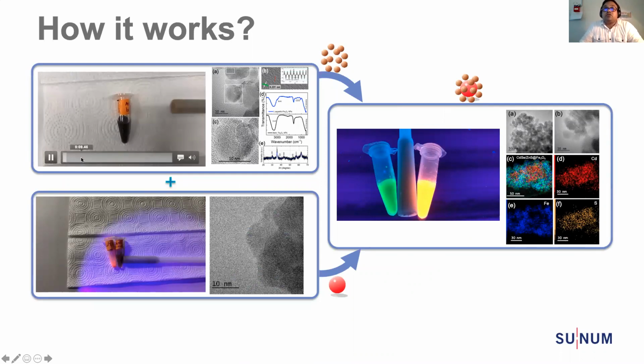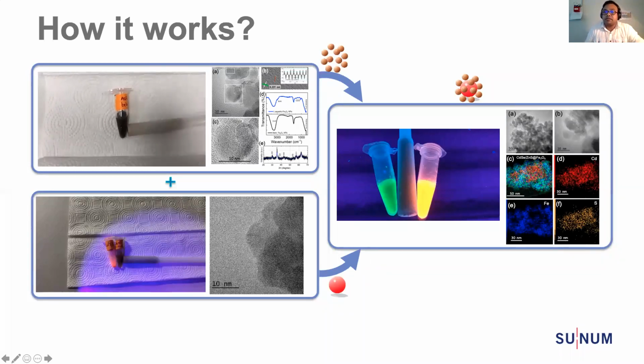First we had to synthesize very precise size-controlled magnetic nanoparticles. We employed density gradient centrifugation as we commonly use in biology. Sucrose gradient, cesium chloride gradient centrifugation. You build up the gradient of concentration of sucrose or something like that. And then when you pull down using a centrifugal force, relative centrifugal force, with the different gradients of concentration of these sucrose or cesium chloride, you can essentially control or separate or isolate specific sizes.